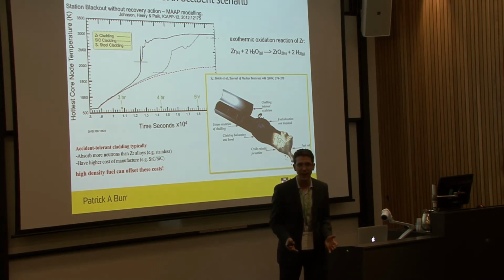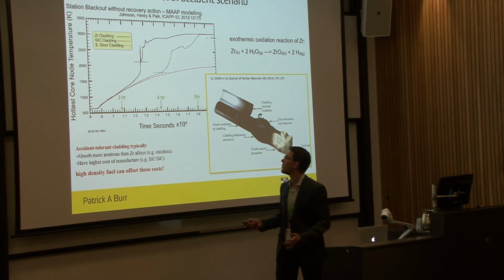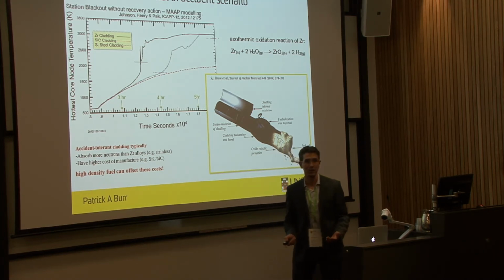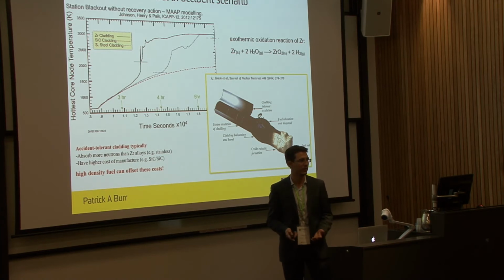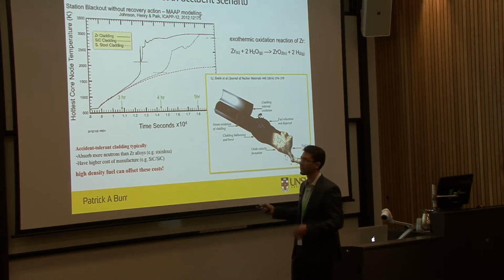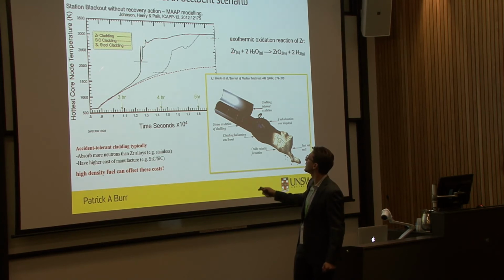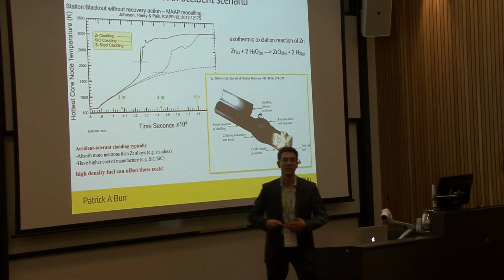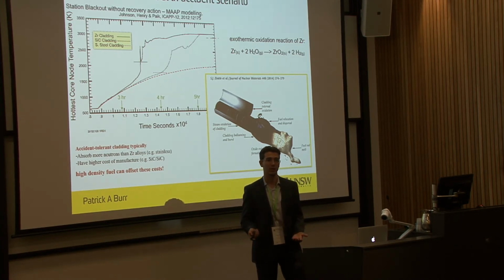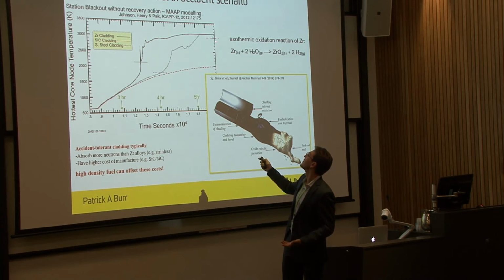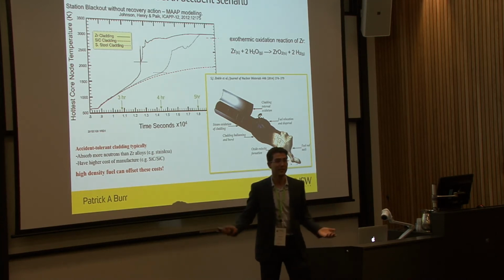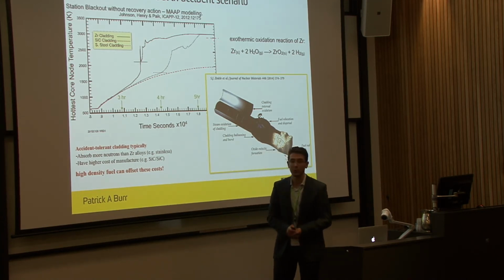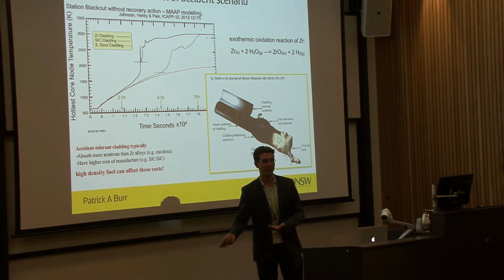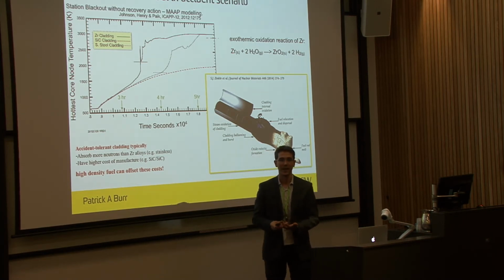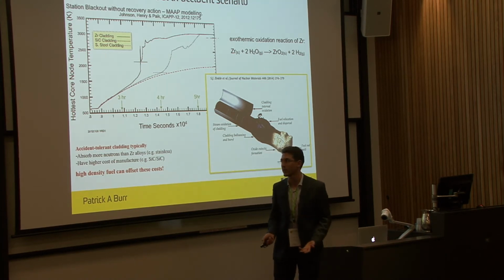You actually can do a lot in half an hour if you go into a station blackout. But we would like to do even better than that, especially if you go through the effort of changing the whole fuel inside a reactor and all the regulations that go with it. So if we look at silicon carbide, you can see that it's got that lovely parabolic curve because it doesn't have an exothermic oxidation reaction, and the melting point is up there, at 3000 Kelvin. So it sounds amazing as a material, and from the oxidation point of view, it is. However, of course, you have to make this stuff, you have to pay for it, and it has to be mechanically strong. So there are the downsides.